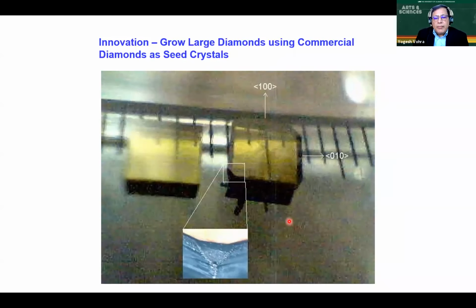So one of the simplest experiments you can do is you take a diamond plate. This is typically a yellow diamond plate, which is doped with nitrogen, and you put it in a microwave plasma, and you can see within a few hours, you can actually enlarge this plate. The size has gone up because of the placement in the microwave plasma chemical vapor deposition system.